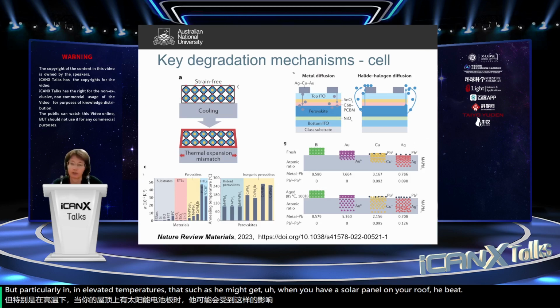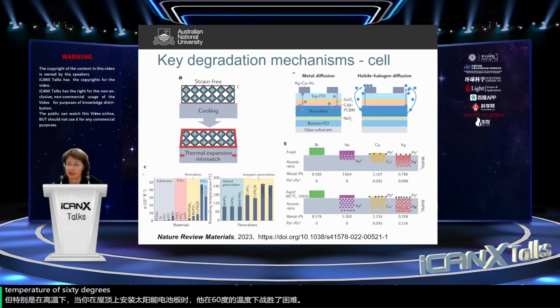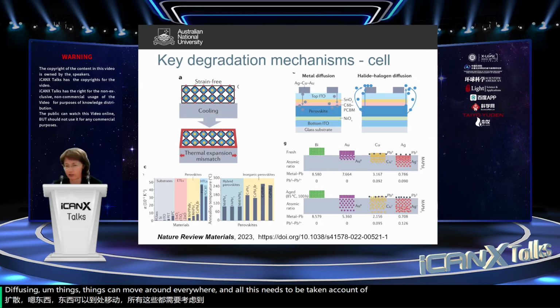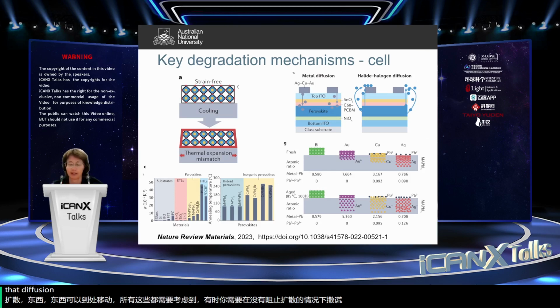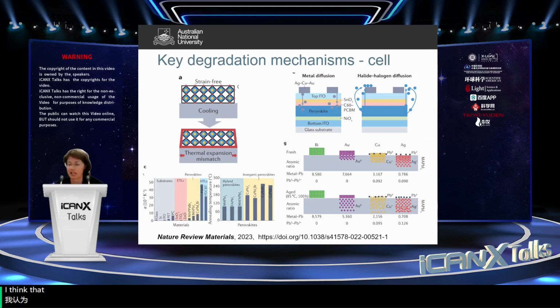You'd be typically looking at a temperature of 60 degrees or so. You'll get metal diffusion into the perovskite. You can get the ions diffusing. Things can move around everywhere, and all of this needs to be taken account of. And sometimes you need to put layers in there to stop that diffusion. So these things can all lead to degradation. So these are degradation mechanisms at the cell level.